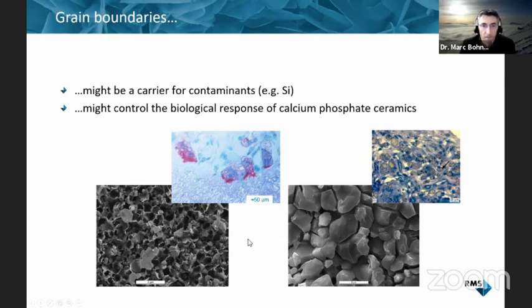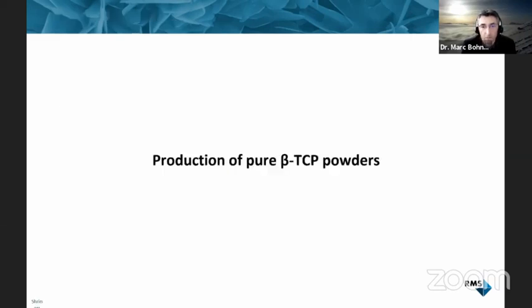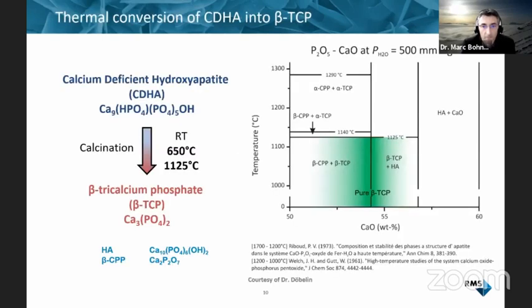So adding contaminants into the structure might have different effects. First, by being released and having a direct biological effect, but also by modifying the way the ceramic is resorbed. So these are the topics we wanted to address in this SNSF project. And to start from the start, we wanted to have a pure beta-TCP material that we could use as a control group, and then to dope this material and look at grain boundary composition and solubility, and also at the behavior of macrophages and osteoclasts.